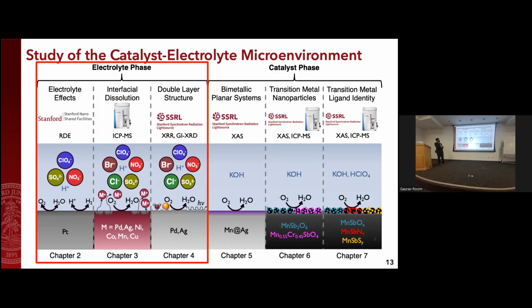I'll just briefly mention, in terms of the catalyst phase, I got to look at how adding a very small layer of manganese on silver affects the oxygen reduction reaction, and actually used X-ray techniques to understand how oxidation state changes affect catalysis. I also looked at these manganese antimony oxide nanoparticles and doping various metals within them to understand how their activity and stability are modulated with online stability techniques. And lastly, a project where I looked at changing the ligand. That is, the oxygen in this case, if we swap that out for a nitrogen or a sulfur, how that affects everything. So those are all catalyst phase things, but I'm going to stick to electrolyte phase today.